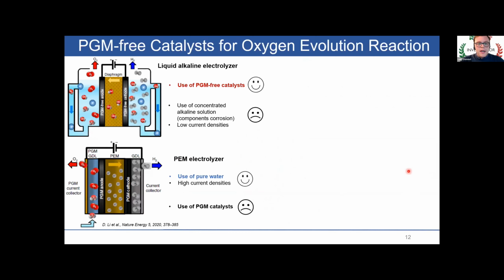I would like to talk a little bit now about my work on the other electrochemical conversion device that I talked about, which are the water electrolyzers for generating hydrogen. So currently, the two widely used technologies for generating hydrogen at low temperature are the liquid alkaline electrolyzer, which can operate with a PGM-free catalyst, but has the drawback of using highly concentrated alkaline solutions and operating at low current densities.